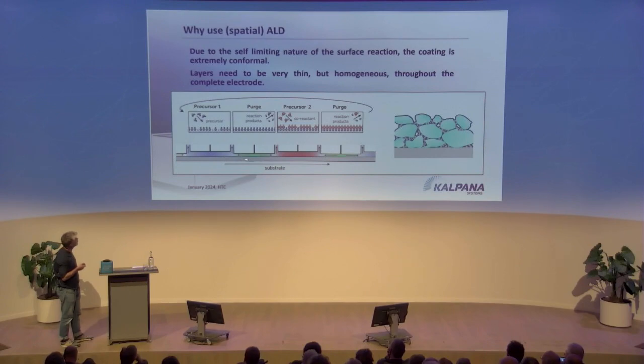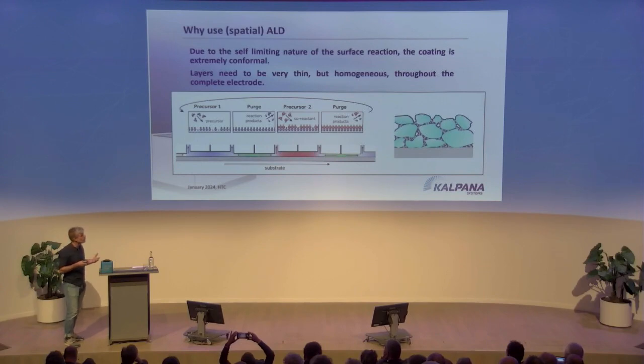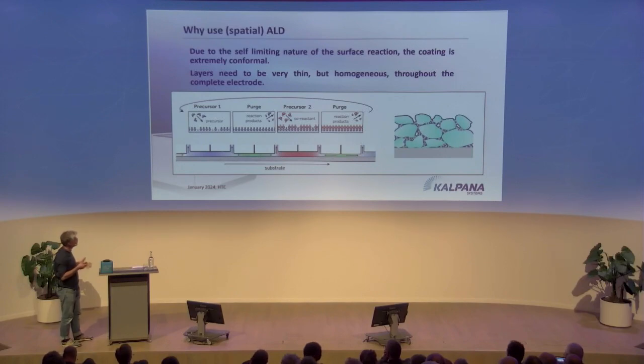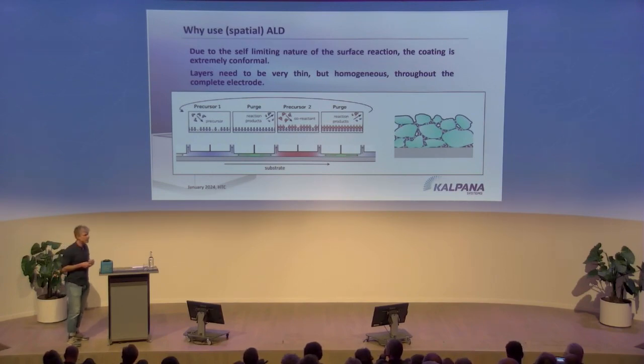For that, you put nitrogen knives, for instance, in between exhausts. And it's very important to keep this gap very small, so to control your substrate and your deposition head very well. And another thing is that if you want to make a significant layer thickness, you need a very long deposition head actually. These four things are what you need to do one ALD step, one ALD cycle. If you want to do a lot, you end up with a very long deposition head.